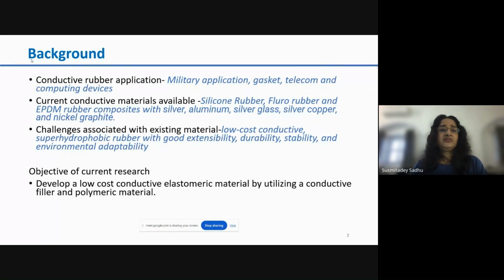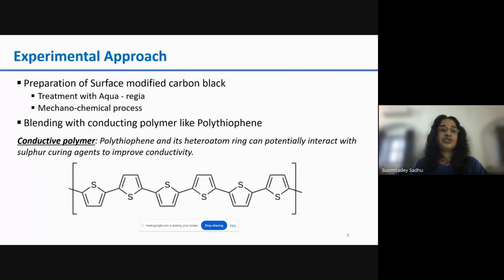So for this work, we have chosen carbon black, and we have modified the carbon black in two different ways in our lab. And along with that, we have used a conducting polymer like polythiophene as the heterogeneous phase. And as a continuous phase, we have used NBR, which is a polar rubber, for preparing the sample.